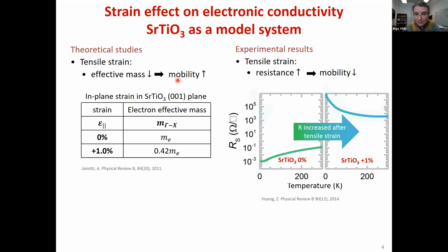And a few years later, there comes this experimental paper, which actually shows the opposite, that when you tensile strain strontium titanate by 1%, exactly the same as the theoretical prediction, the resistance actually increases. So there is an apparent inconsistency between this previous theoretical and experimental work, which assumed only free electron dominance in strontium titanate that would give rise to electronic conductivity through a band-like model,